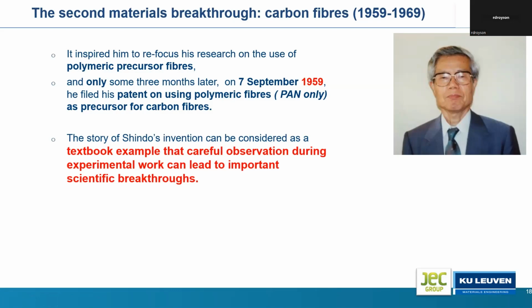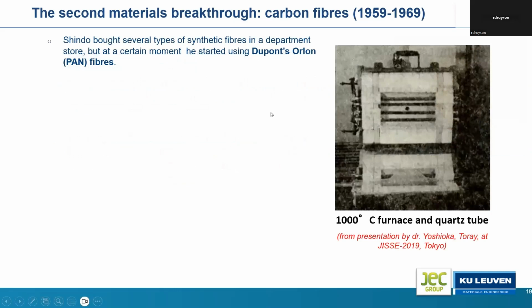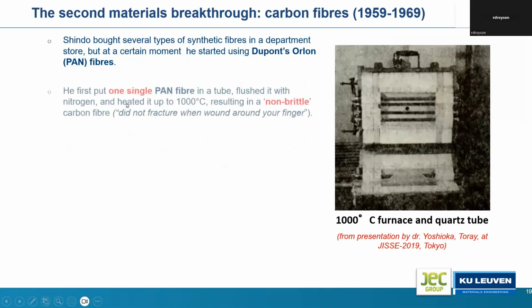And I will take a few minutes to take you through this invention of Shindo. So he said, okay, I need good fibers, and I will try different types of polymeric fibers to make carbon fibers out of them. And he finally ended up with DuPont's polyacrylonitrile fibers, the Orlon fibers. And he took one of these fibers, one single fiber, and put it in a tube, flushed it with nitrogen to get rid of the oxygen as much as possible, heated up to 1000 degrees, and he had immediately, or after a few trials, a non-brittle carbon fiber. And he writes in his report, it did not fracture when you wind it around your finger.